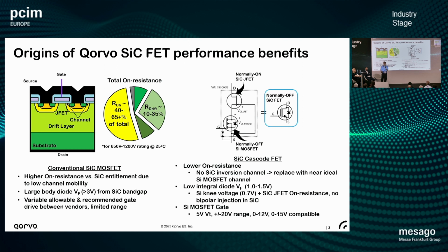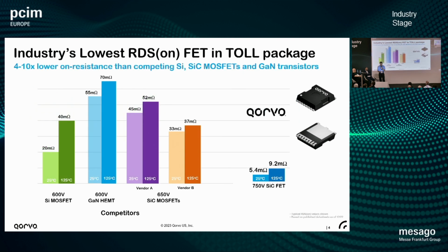Very few people want to use normally on JFETs. So in order to deliver a normally off device, we use the cascode arrangement. And you can see from the picture behind you, it involves putting a specially designed low voltage MOSFET in series with the device, co-packaging it, so from the outside, you drive it similar to a silicon device. So what we can achieve with that technology, the reason why we do all of this, is ultimately we can deliver very low resistance devices if you do things this way.